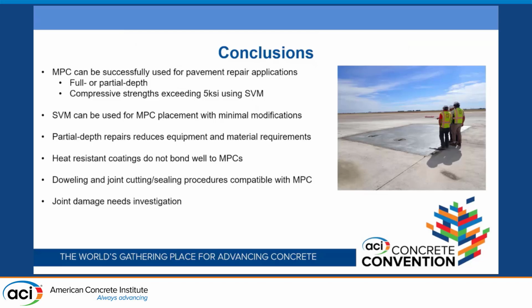So conclusions: MPC can successfully be used for pavement repair applications, full or partial depth. I think we preferred the partial depth, even though there's a lot of jackhammering involved. The simplified volumetric mixer can be used for it. Partial depth repairs reduces equipment. Heat-resistant coatings did not work. Doweling and joint cutting, so basically the constructability of airfield pavements, a lot of that can carry over to MPCs, and then the joint damage needs investigation.